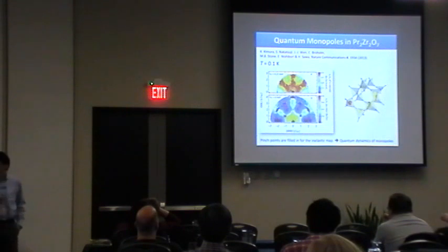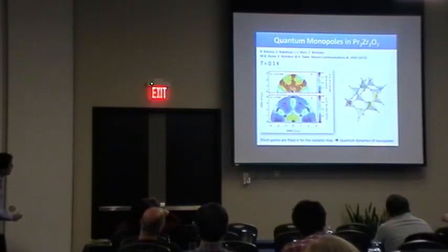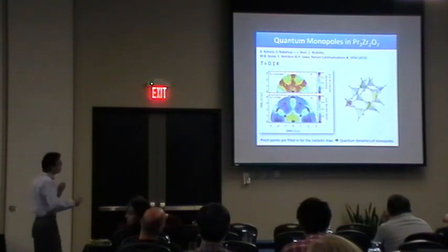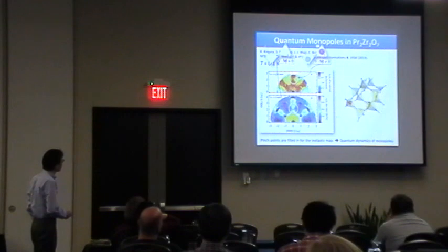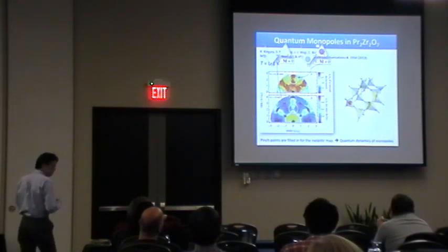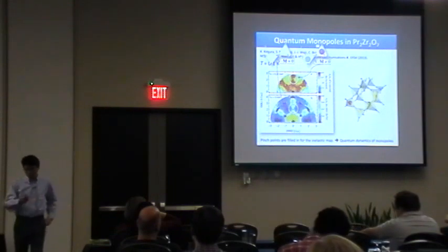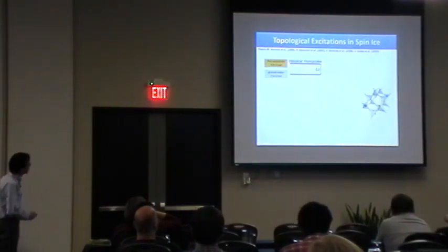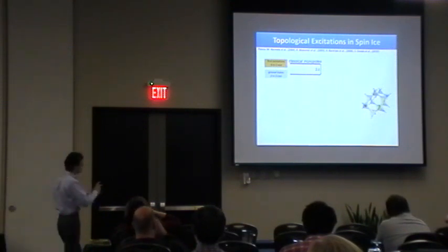So we can visualize the quantum fluctuation in momentum space, and it looks like this. This is quite a lot brighter. This red signal is much brighter than the elastic channel. This means that if you provide energy into the material, a lot of excitation happens inside the material. What kind of excitation? It turns out, if you look at the high symmetry point 200, this pinch-point-like structure disappears. So this means that you create monopoles, and they form such excitations inside the material as quantum fluctuations. And this is quite consistent with recent theoretical development. The ground state is two-in-two-out, which is frozen, just like an ice state.